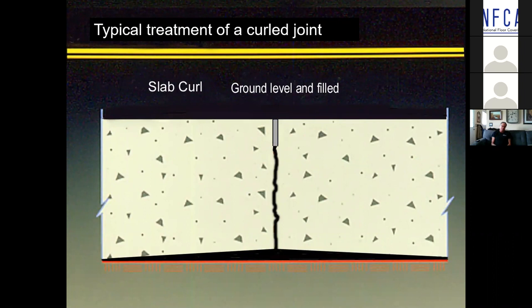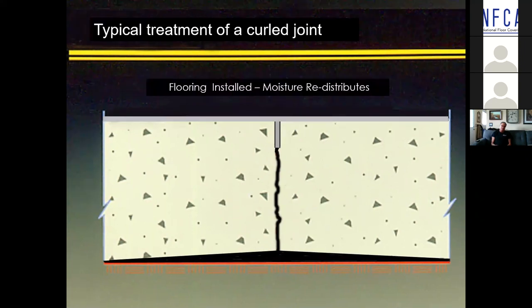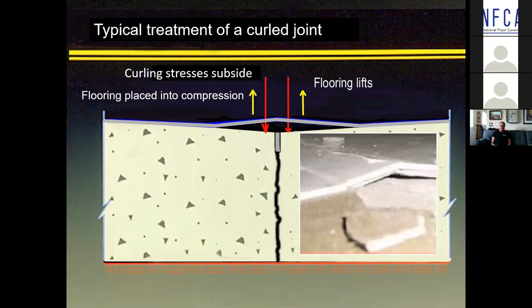More often than not, people come in, if they've checked the slab, it's curled, they grind the surface level, or in some cases they use a leveling compound. But they forget or don't consider that if the joint is raised up, there's a void underneath that slab. There's a hollow area. Again, only back several feet each side of the joint, but it's hollow. Now you come in, you put down a flooring or a coating. Moisture is always attempting to seek a state of equilibrium. And as it attempts to seek that equilibrium, it redistributes. And as it redistributes up into the drier portion, the warping stresses subside, the slab sections go down because they're not being supported underneath, and it puts whatever's over that joint into compression.